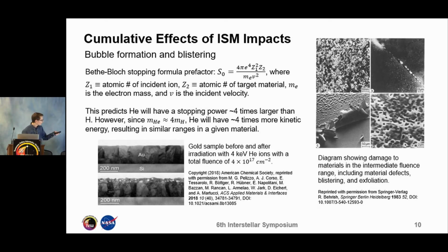These are some figures which show what these phenomena look like on your right, I guess. You see a gold sample after irradiation from helium ions at 4 keV, and you see the bubble formation below the surface. And this is actually at a fluence which is comparable to what we expect to see. And then the diagram on the other side shows damage in the intermediate fluence range, and you can see blister formation and exfoliation and bursting at the surface as well.